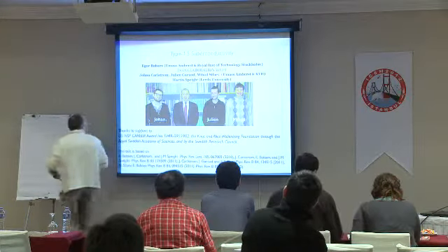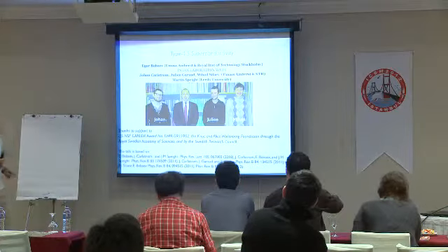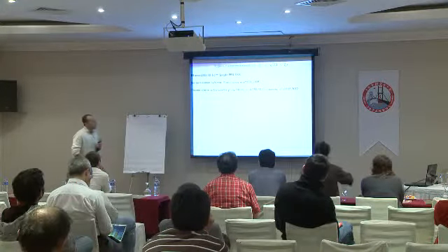All right. So the idea of type 1.5 superconductivity is very simple, and can be written in one line. If you have multi-component systems, in general you'll have several coherence lengths. And there is no fundamental reason which can prohibit the occurrence of a situation where one coherence length is smaller than the penetration length of the magnetic field, and another coherence length is larger than the magnetic field penetration length. And it was termed by Victor Moshchalkov as type 1.5 superconductivity.